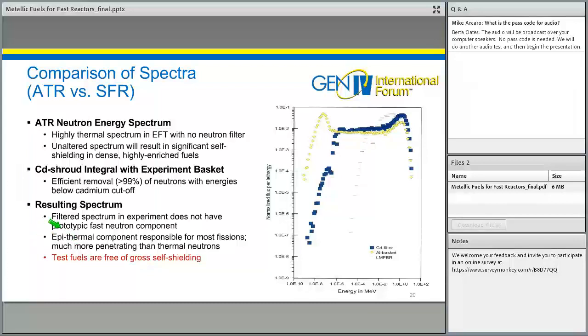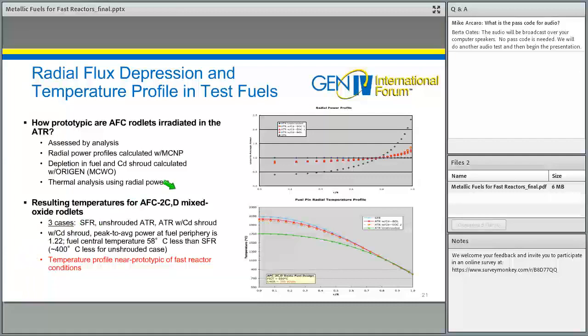Most of the fissions are being driven by epithermal neutrons, which are much more penetrating in these high-density fuels than thermal neutrons. And what we've done is eliminated the gross self-shielding that these fuels would experience if we just put them into a thermal spectrum. And these curves attempt to show what we're achieving. So this is local to average power plotted versus fuel radial position. So this here, 0, is the fuel center line, and out here at 1 would be the fuel surface.